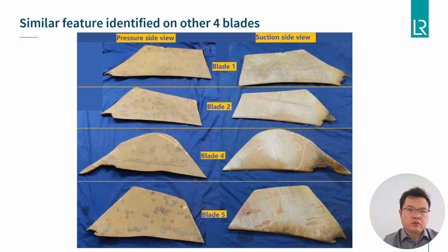After investigating the most damaged blade, we recommended to the client to send us the sections from the remaining 4 blades from the same propeller for further investigation. And not surprisingly at all, we found very similar features as the previous blade. The fractures identified on the sections from all 4 blades are also predominantly due to the propagation of fatigue fracture originating within weld repairs to the blades.